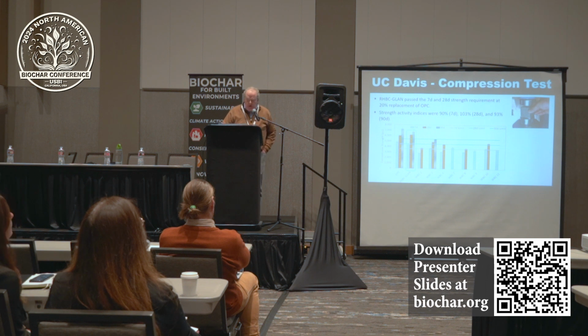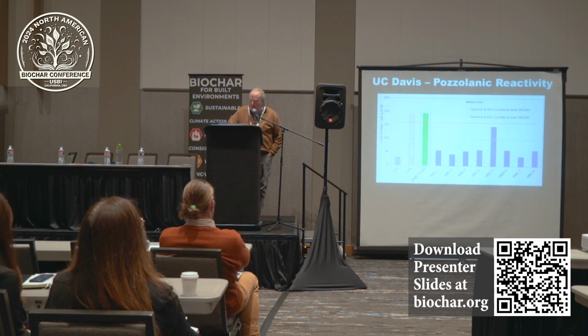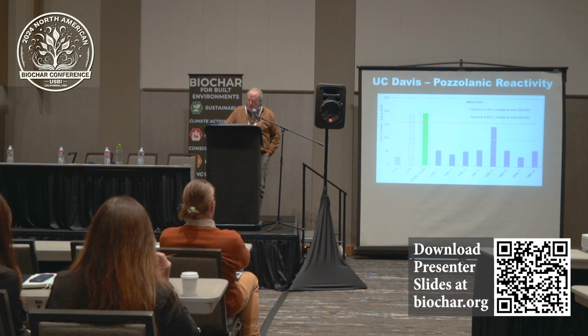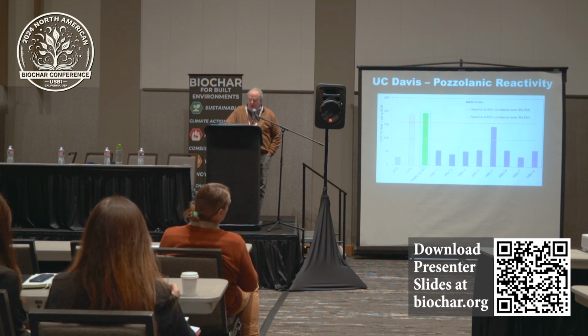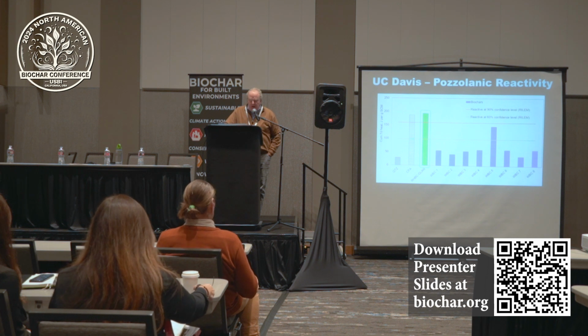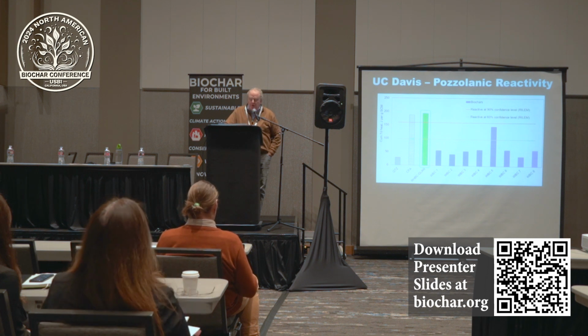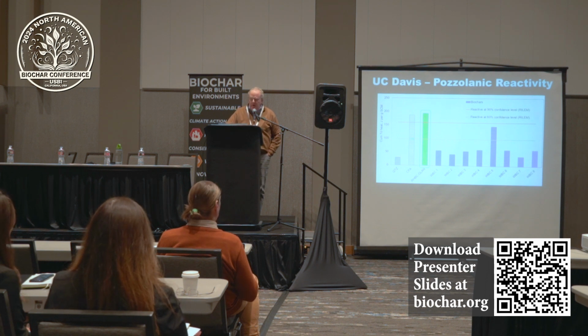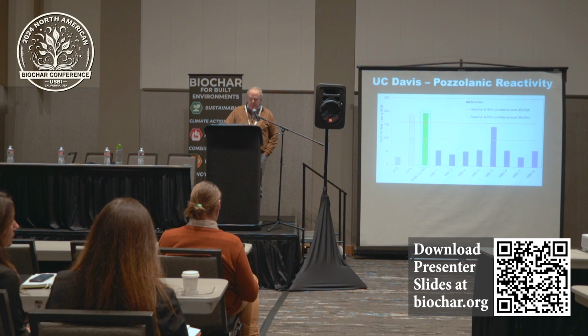One of the key things here that Lori touched on, and that was a real driver in this, is the pozzolanic reactivity, and this is really solely because of the high silica content. So while it doesn't create a great high carbon content, the rice hull biochar does have some interesting properties that can be leveraged in the silica for us in water filtration and also here in cement, because that pozzolanic reactivity, as Lori said earlier, is really what drives the glue and the cementitious properties of the material.